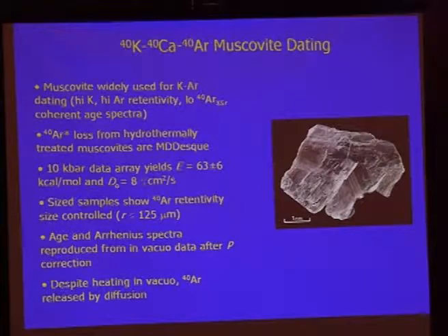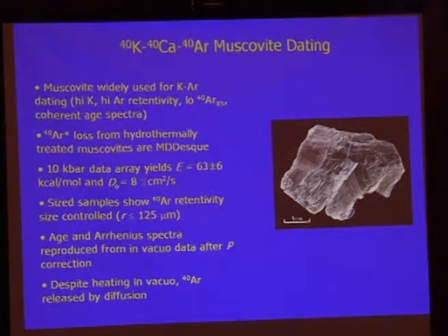Okay, so actually, muscovite is a bit of a rascal because it actually is more retentive of argon, seemingly, than biotite in nature. But remember, I said ideal diffusion experiment. We put the K-feldspar in the vacuum. It's happy up to 1100 degrees, and then we melt it. This guy here breaks down at relatively low temperature. If you don't cook a muscovite up in the lab to 600 degrees, you're not going to see any argon movement. You take it above 700 degrees at a couple of kilobars, and it's going to turn into sanidine plus quartz. Okay, so this is a rascal.